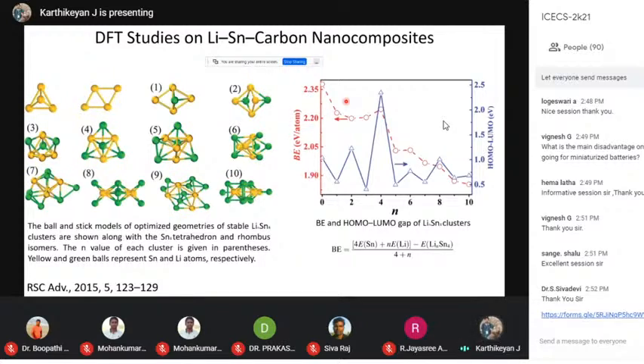Computationally, it is impossible. Especially in India, we don't have that much computing power. We had very small clusters, so we wanted to use an atomic cluster as a model to mimic this reaction and see what is really happening in this nanocomposite. So we have chosen a 4-atom tin cluster that is shown here. So this is going to mimic a tin nanoparticle, we can say, and then we are going to add lithium to this. So these numbers in the bracket give the number of lithium atoms added to the tin clusters. So when you add lithium to tin clusters, initially the rhombus shape was stable.